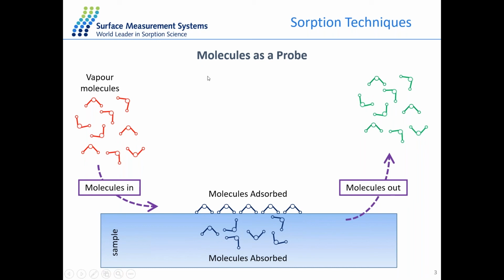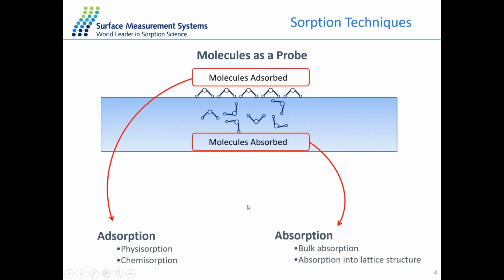So in case of the interaction of the probe molecule with the solid material, it will be either adsorbed on the surface of this material or absorbed into the bulk of this material. For the adsorption on the surface, it will be either by physisorption or chemisorption, depending on whether a covalent bond is forming or it is just loosely bound on the surface. So from the adsorption interaction, we can then determine lots of surface-related properties, for example, the surface area or the surface energy of this material at certain conditions.